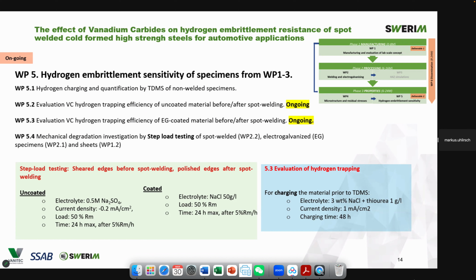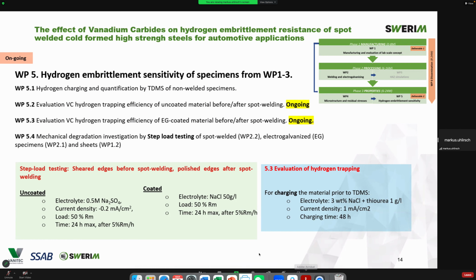Some smaller parts of the evaluation are still ongoing, but we're going to show some results in later slides. Just a comment here in the green box, it says polished edges. We polish the edges because we want to have cracking in the spot weld during the test and not on the edges, where different surface roughness might increase the amount of hydrogen there.